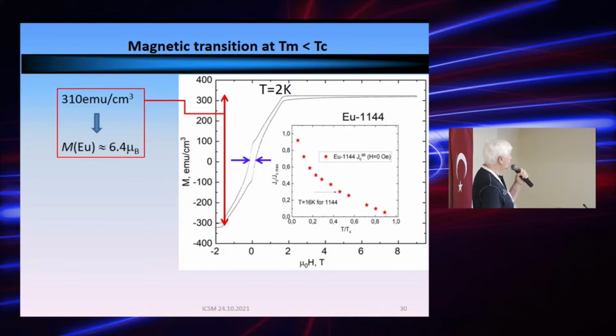Indeed, when we take measurements of the magnetization as a function of magnetic field, we see here the nice hysteresis loop, which is intrinsic to magnetic materials, and inside there is a hysteresis which is due to superconductivity. This hysteresis disappears when you go to the critical temperature. Just roughly from the amplitude of the saturation, you can estimate the magnetic moment of the europium, which is 6.4 Bohr magnetons, and this is roughly consistent with the textbook value of 7 Bohr magnetons.